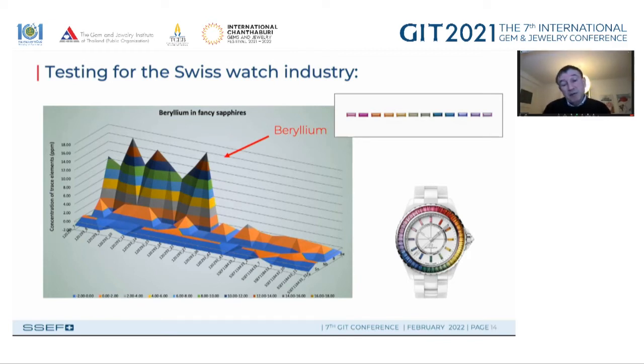What we have to monitor this situation are elements like tantalum, titanium, niobium, so-called high field strength elements, and they are all very low, even below detection limits, which indicates that this beryllium is due to a diffusion process and not linked to any kind of nano inclusions which have brought some beryllium naturally into the stones.